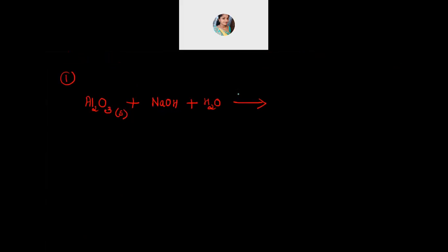Yes. Now see the temperature and the pressure which I was telling you. The temperature taken over here is around 473 to 523 Kelvin, and the pressure maintained is around 35 to 36 bar. When you maintain these conditions, it is found to give you a soluble compound.